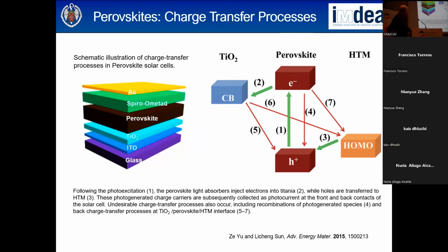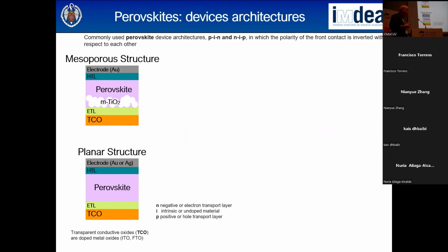What happens is that upon photoexcitation in the perovskite, the electrons can go to the titania, which is the electron transport layer here. At the same time, the holes are moving to the hole transporting materials. But then there are other expected but undesirable processes like charge recombinations and all other kinds of charge transfer processes, which I will not go into detail right now. These are the typical architectures of the perovskite devices.